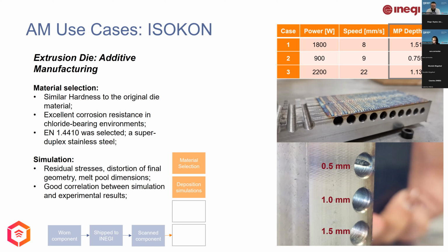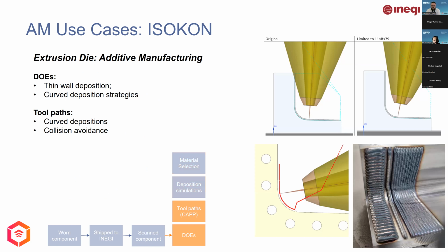As can be seen in the table and the figure on the right, the experimental results have very good correlations with the simulations. Following this work, a set of experiments was conducted to evaluate how the depositions would behave on a curved surface. The objective of these experiments is to understand how different strategies affect the final results and what would be the best tool paths to repair the die. Special attention was also put, as mentioned by Marco, on creating strategies to avoid the collision between the tool head and the part being worked on.